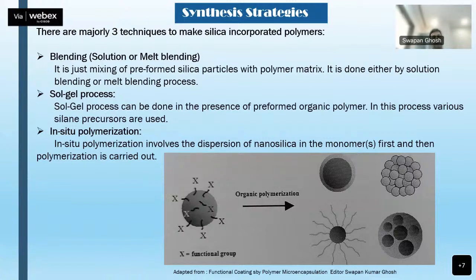But in this case, if you have to have silica inside a polymer matrix, then you have to use polymer latex, and in the presence of that, we have to conduct the sol-gel process. The third one is in situ polymerization. In this process, nanosilica is dispersed in a monomer solution, and then a polymerization can be carried out. Now, in general, when you would like to take an inorganic material, in this case silicon oxide, into a polymeric matrix, the first stage is very often that the surface of this silicon oxide particle must be modified with certain functional groups.